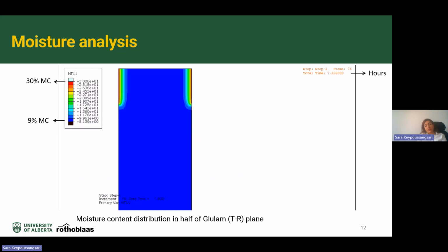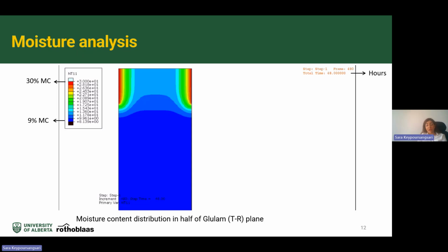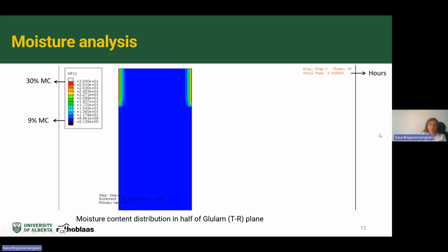This result is a sample of how moisture is distributed inside the glulam when only 2 layers of glulam are exposed to the water. After a few hours, you can see these areas, which are red. They reach around 30% moisture content, which is the fiber saturation point. And after 48 hours, you can see how moisture can be distributed inside the wood and our samples when only 2 layers of glulam are exposed to water.